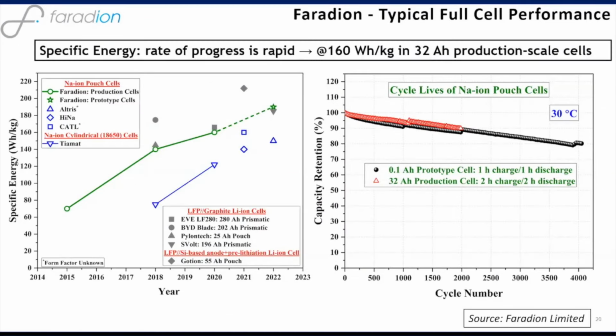Through third-party testing, the 0.1 amp-hour prototype pouch cell from FARADION delivered an energy density of 190 watt-hours per kilogram at a 1-hour charge and discharge rate, and retained over 78% of its initial capacity after 4,000 cycles at 30 degrees C, while the company's 32 amp-hour production line cells recorded an energy density of 160 watt-hours per kilogram at a 2-hour charge and discharge rate, and is forecasted to deliver between 2,300 to 3,000 cycles.